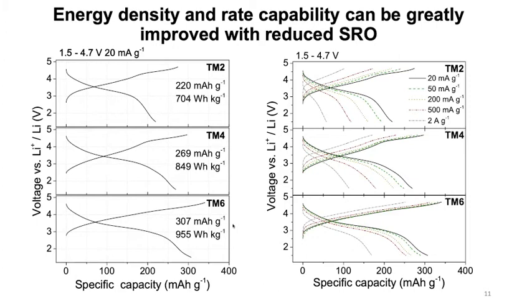At the same time, the rate capability can also be significantly improved. For TM2, when cycling between 1.5 to 4.7 volt, the capacity reduces around 60 to 70% when you increase the rate from 20 milliamp per gram to 2 ampere per gram. This capacity reduction is reduced to slightly more than 50% for TM4, and can be further reduced to around 40% in TM6 when you increase the rate all the way to 2 ampere per gram.